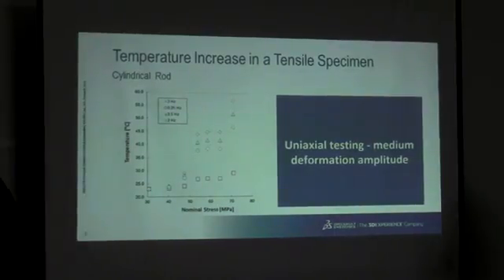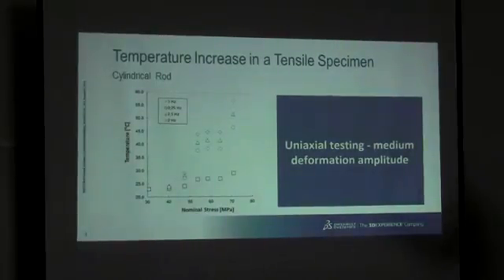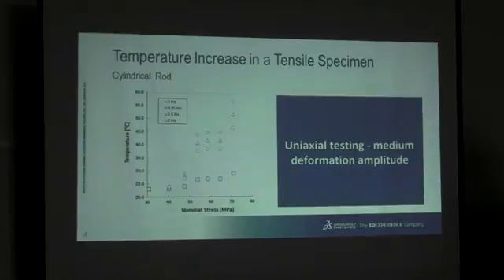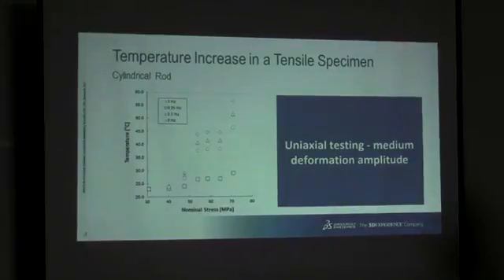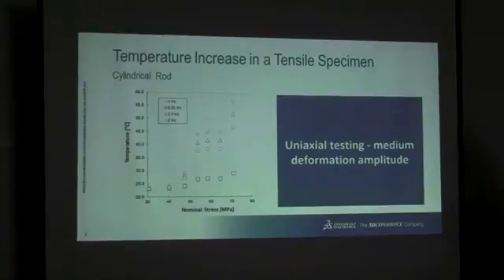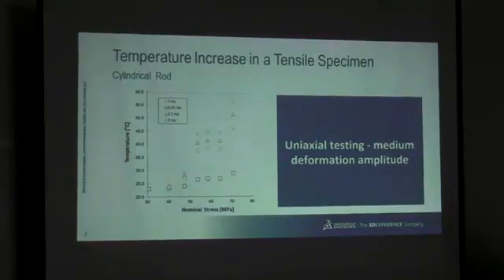But what we haven't considered then is that temperature might actually fall and then it might actually rise again and so on and so forth. The third and worst scenario is if the amplitude is so high that you cause thermal failure instead of mechanical failure. That means that when you think of plastics, you have to think thermomechanically all the time. What I want to show you here is an example of uniaxial testing where we have applied a medium deformation amplitude.